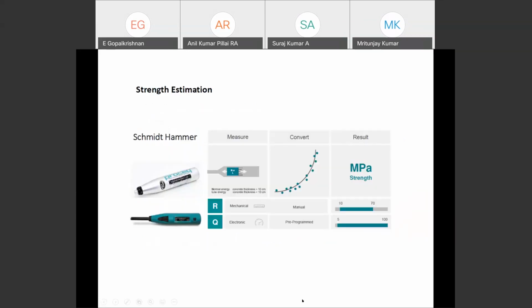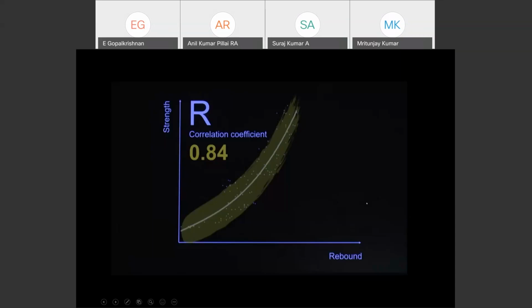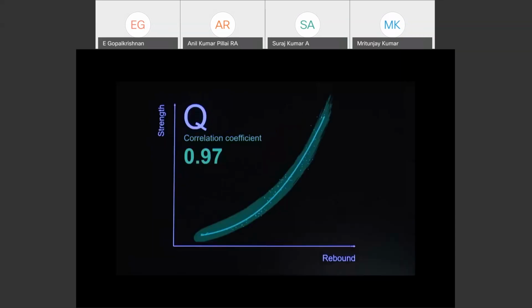When you compare the latest one, both correlate to the compressive strength. However, the original Schmidt hammer can measure 10 MPa to 70 MPa, whereas the new one can measure 5 MPa to 100 MPa, so the lower and higher limits are extended. Now, what is the coefficient of correlation? 0.84 for the original, and we can see that the latest Q value will give a 0.97 coefficient of correlation compared to the R value, which is 0.84.